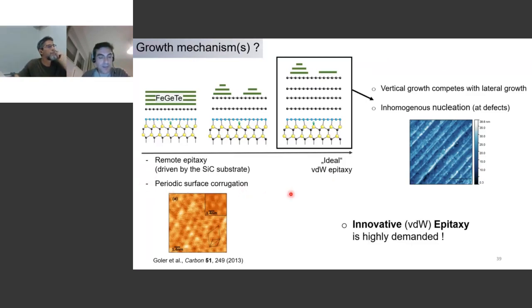Another thing that we know, this epitaxial graphene has a periodic corrugation that is created by the buffer layer underneath. It's not represented here, but on a large area, we have a surface that looks like that, where this kind of undulation is promoted by the buffer layer. The thicker you grow your graphene, the farther away you get from both the buffer layer and silicon carbide. And so you go closer and closer to a case of ideal van der Waals epitaxy, where the growth will have the other problems that we see in the boron nitride, like that you start having more vertical growth instead of lateral growth and inhomogeneous nucleation. That's what you see here, where you see these FGT islands that are growing close to step edges and so on, very similar to the case we observe for hBN and graphene.